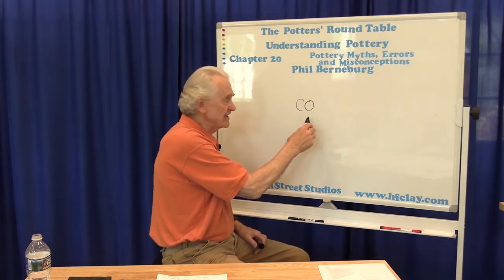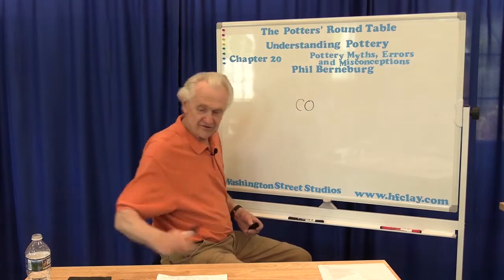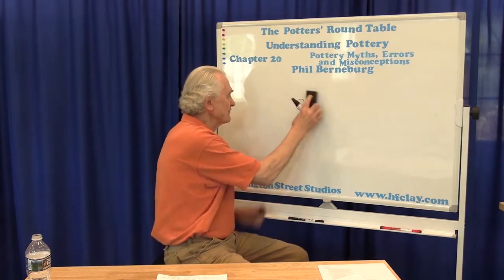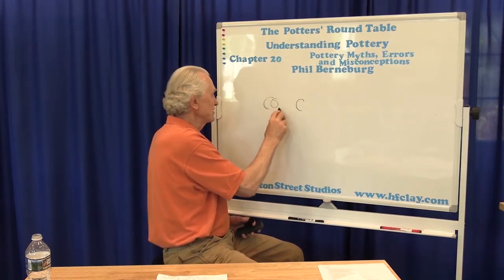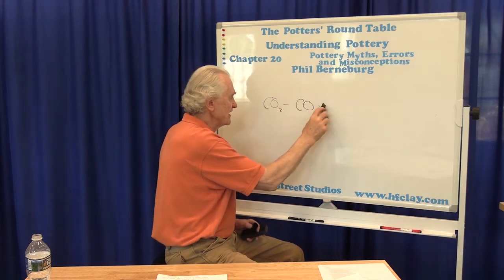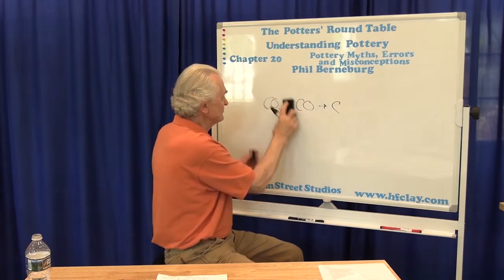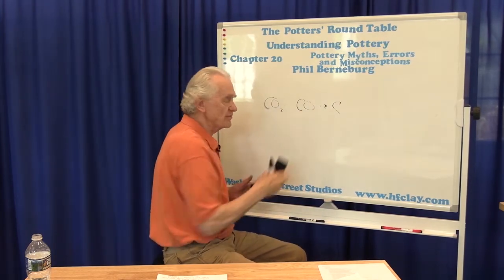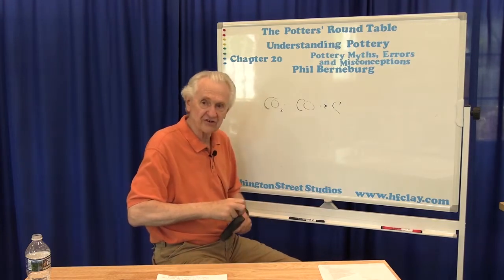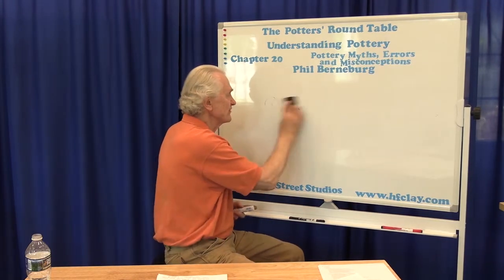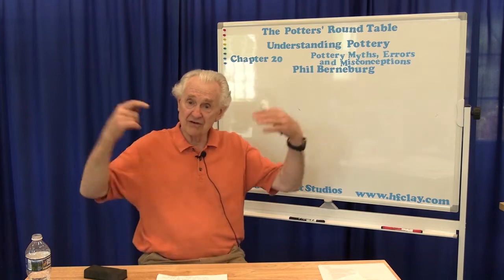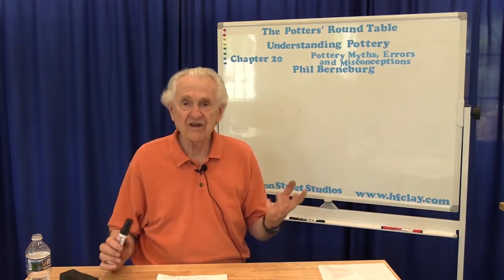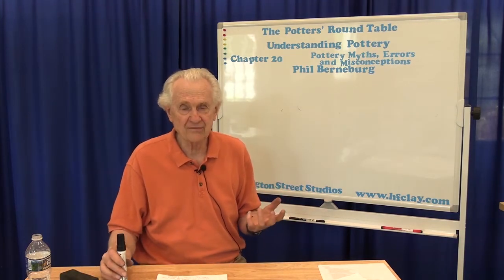If I go into even heavier reduction, first I go from CO2 to carbon monoxide, and then I go to carbon. So I basically strip the oxygen and I end up with carbon. Well, soot. Soot doesn't do any reduction. Soot just accumulates on everything. You see the black soot coming out, maybe the cracks in the kiln. The only reason that you'd want to intentionally make soot is if you're trying to do carbon trapping.